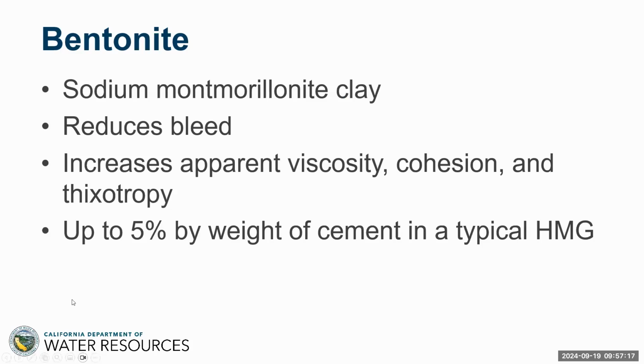Okay, so just a tiny wee bit of background here. For ground treatment, either injecting rock masses or soil, we don't use neat cement grouts anymore. That's a thing of the past. We use what are called balanced high mobility grouts. And these would comprise bentonite, cement, and water, but also, as we're going to see in a second, a viscosifier, which is a gum, and superplasticizer. So, for example, the bentonite and the viscosifier thicken the grout, but we need the super P then to make it more fluid. So we're basically balancing the impact of each of these different materials. And then in some cases, some contractors choose to use ash or silica fume and other materials like that.